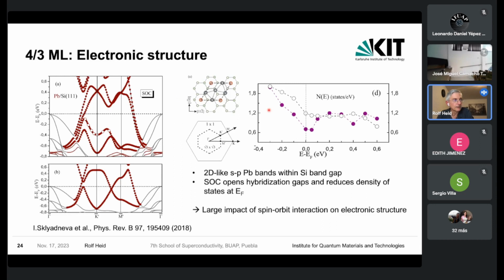And so you can do the same analysis. You can look at the density of states, for example, as a function of energy. We have also compared, in this case, calculations with spin-orbit interaction and without spin-orbit interaction to see the effect of the spin-orbit interaction on the various properties. And in this case, we find a reduction of the density of states when one switches on the spin-orbit interaction, which is due to the occurrence of hybridization gaps in these metallic lead bands.